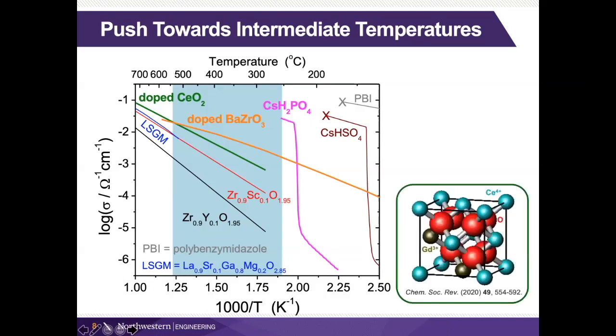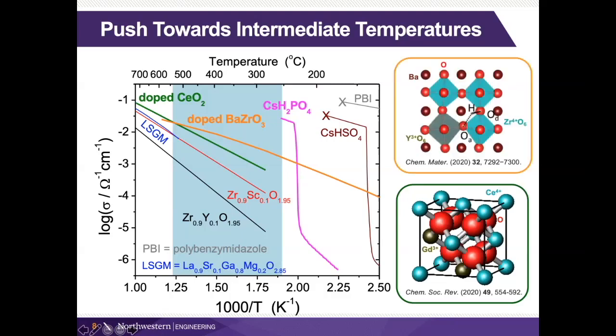I'll just show you those structures. The ceria material here has oxygen vacancies. That's why it's a very good oxygen ion conductor. The doped barium zirconate is a material which has a perovskite structure, and we dope that such that it has some sort of trivalent dopant, and that is charge balanced by having protons incorporated into the structure. They make these hydrogen bonds and they can move around through the structure,